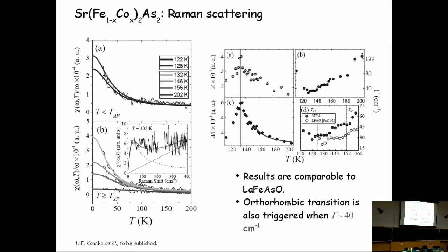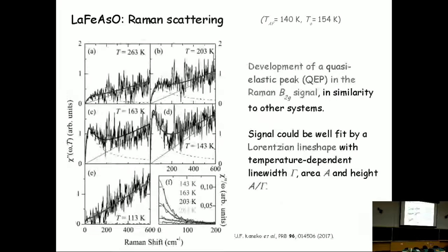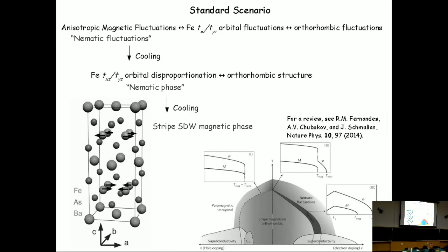Could you just remind me, in the antiferromagnetic phase, do the spins lie in the plane or perpendicular to the plane? They lie in the plane. They lie in the direction of the antiferromagnetic order. So they lie in the antiferromagnetic direction and perpendicular to the other direction, so there's choices to make. Both in the plane. And so they're locked to the stripe. Yes, they're locked to the momentum for the stripe.